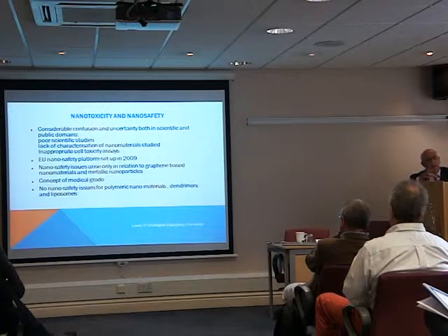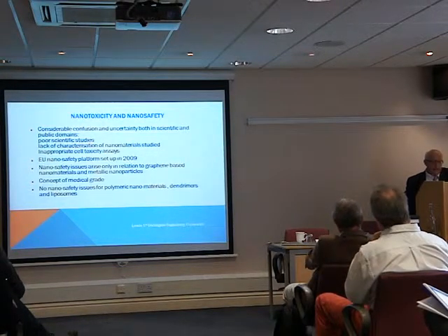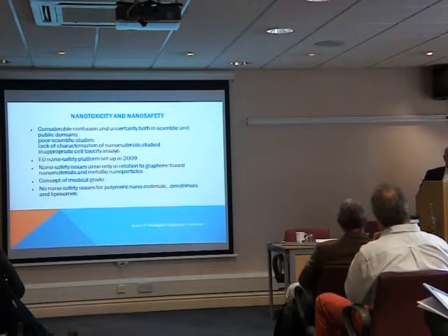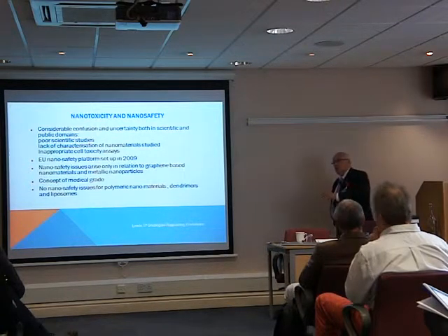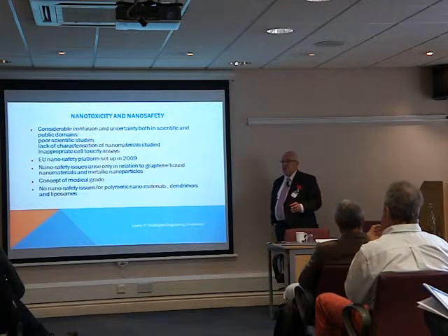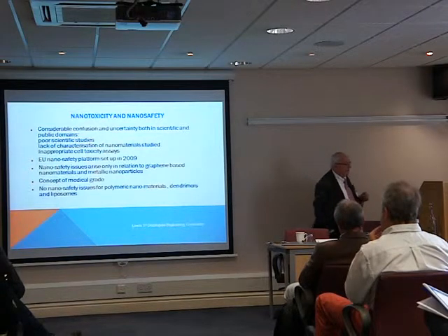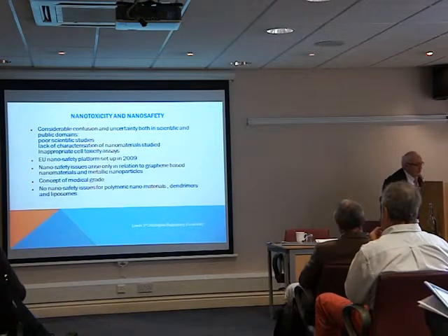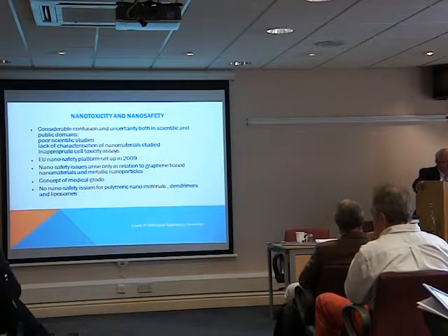The other thing that my group in Pisa, headed by Dr. Li-Jun Wang, who is here, found is that very often the cell toxicity assays used are inappropriate in the sense that the chromogen, the color substance they use, actually interacts with the nanomaterial. So you get spurious readings. So this is very important and has led the EU to the formation of a nanosafety platform.